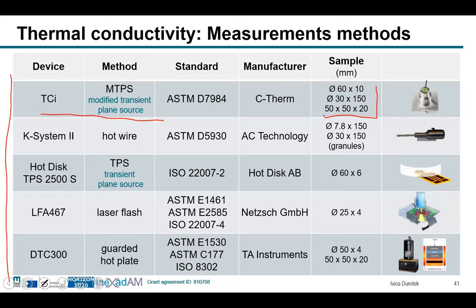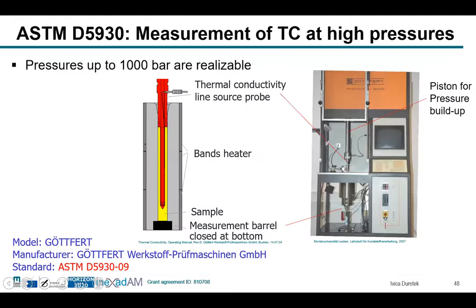In the melt region or melt state, we use, for example, K-System 2. This is a method based on the hot wire method. And then the other methods like TPS, laser flash, and guarded hot plate. One advantage of the hot wire method is that it can be used, for example, at a high pressure capillary rheometer. And with this device, you can measure the thermal conductivity dependent on temperature and pressure.